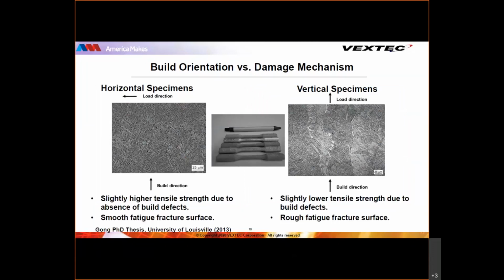I think we have known that in AM processes, there is a dependence or variation in fatigue performance based on build orientation. Again, here's an example I'm showing of EB Ti64, with two build orientations. On the left-hand side, the build direction is vertical, and the loading direction is orthogonal to the build direction.